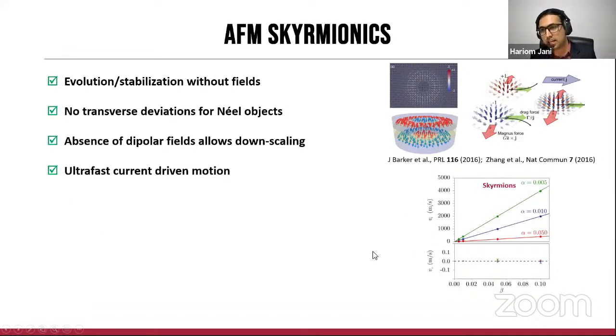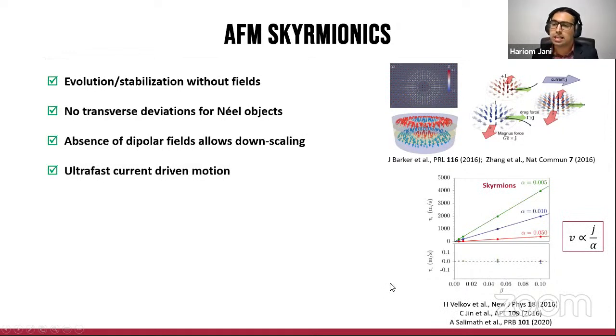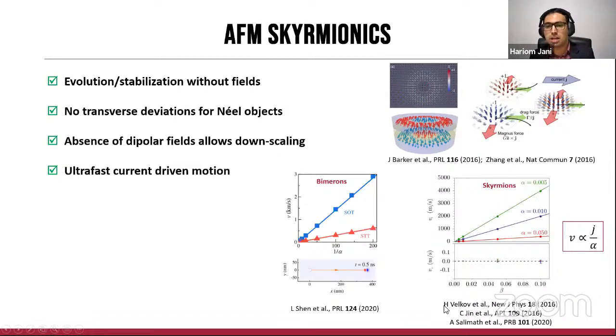This was not only investigated in these works, but also some important works. And the key feature to note here that I would like to draw your attention to is that the speed of topological textures scales with, of course, the current density, but is inversely proportional to the Gilbert damping constant. And therefore, this allows us some very interesting opportunities to achieve ultrafast physics. This is not only for skyrmions as shown here, but also for textures such as bimerons, which I've illustrated before. And these also exhibit ultrafast dynamics.